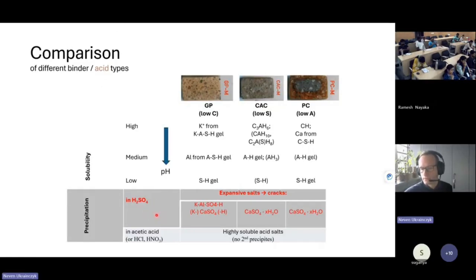Yeah, here I also compare it with different acids that you have here. With Portland cement, you would have crystallization of ettringite at the beginning and later gypsum crystals. Alumina cement also has gypsum crystals inside. This is what we also saw in this publication in CCR when we compare those degradations after in situ sewer exposure. But here you would have also gypsum, but also some alum salts. Those are the potassium alumino sulfates. I think they are called alums in geochemistry. And with acetic acid, you don't have any soluble salt precipitating, but you have the complexation, which makes all the minerals even more soluble.